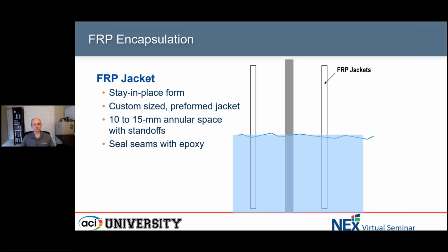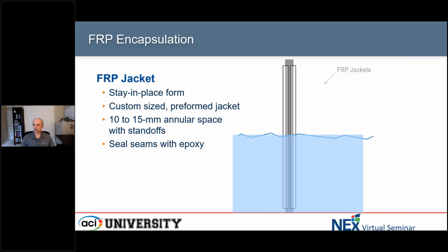So the jackets, or these forms, are FRP materials. They're preformed. Oftentimes they're custom built to match the overall shape of that structure. I'll show you some examples of that here towards the end. And they're designed to match the shape with a very slight, just slightly larger than that existing structure, so that you can fill that space between the jacket and the existing structure with some type of grout material. So the jackets are placed around the structure. Oops, sorry, that animation didn't work too well. But those jackets would be placed around the structure.